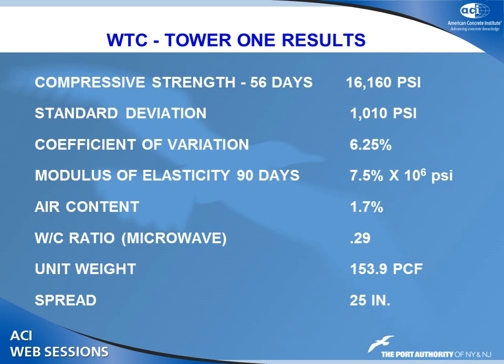Here's the modulus of elasticity, 7.5, not too bad. Air content, great. Water cement ratio, 0.29. Now, that 0.29 is not make-believe. We actually do the microwave test. I know there are people in the audience here that don't like it, say it doesn't work. It works. It's a great test. We use it all the time. And it gives you a good reality test when you're doing high-strength concrete or concrete that you want durability for.